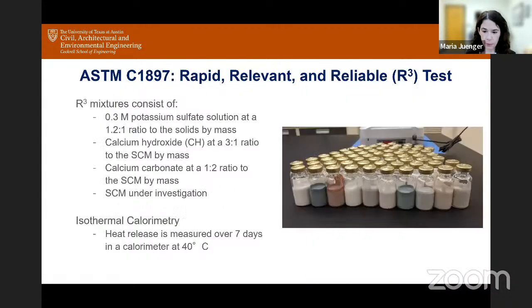They also have overburden. In terms of evaluating these materials, one of the first things that we do in our lab is we run the R3 test, which started out being called R3 because it's called the Rapid, Relevant, and Reliable Test, a very optimistic name. And it's now standardized under ASTM C1897. So these mixtures consist of mixing your supplementary cementitious material with a potassium sulfate solution, calcium hydroxide, and calcium carbonate.